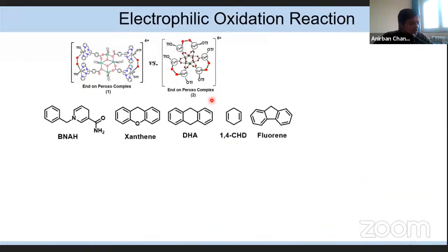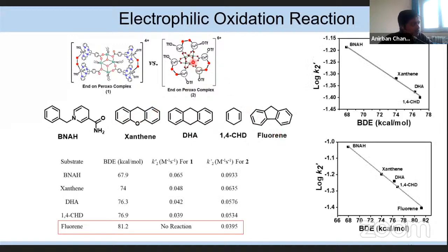Now, interestingly, I checked some electrophilic oxidation reactions with these substrates. Generally, metal peroxide species are not known to show any kind of electrophilic behavior. Very few examples are known in literature where any kind of metal peroxide is showing electrophilic behavior. But in nature, metal peroxide species are known to show the electrophilic behavior. So when I tested my complexes with this substrate, I showed that my complexes react with the electrophilic substrate. These two intermediates act as an electrophilic oxidant towards these different substrates.